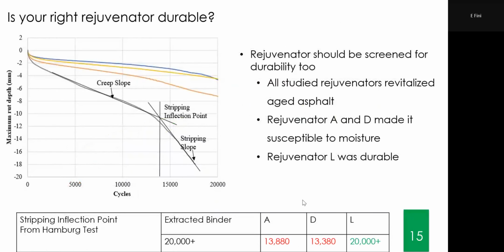One other test that I want you to pay attention to, if you end up working with different rejuvenators, is always about moisture. Many of the rejuvenators, especially those that are bio-based, may have molecules that are moisture susceptible. So in this case, we had two scenarios, and in the previous slide, I mentioned A, D, and L were the ones that changed both crossover modulus and crossover frequency. So now we are just looking at these three. When we did the Hamburg test, only L could go to 20,000 cycles for the stripping inflection point. The rest of them were lower. And funny enough, the extracted binder, which is the aged binder itself, was 20,000 plus. So the extracted binder, the aged asphalt, did not have any problem.